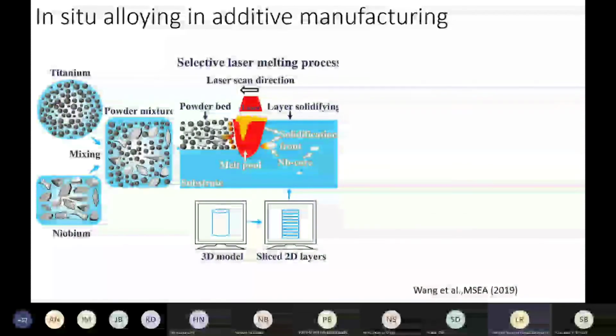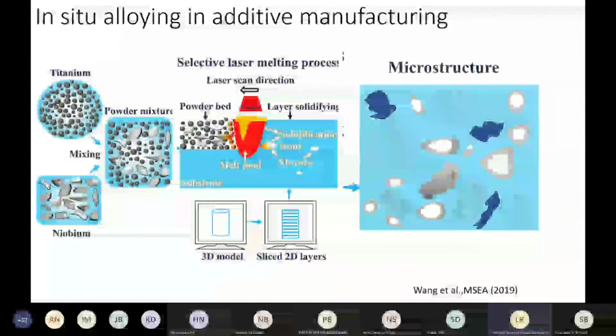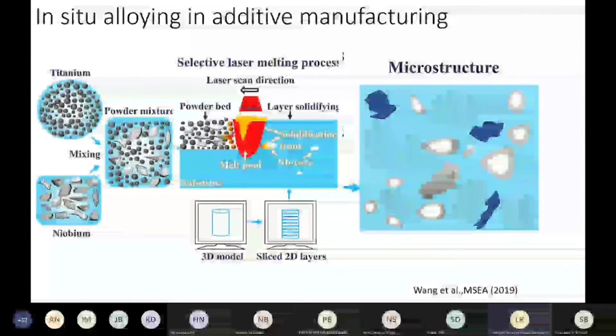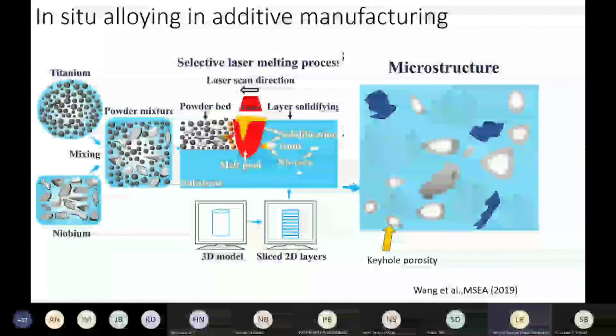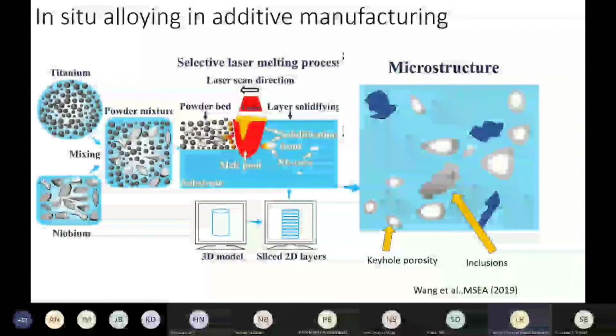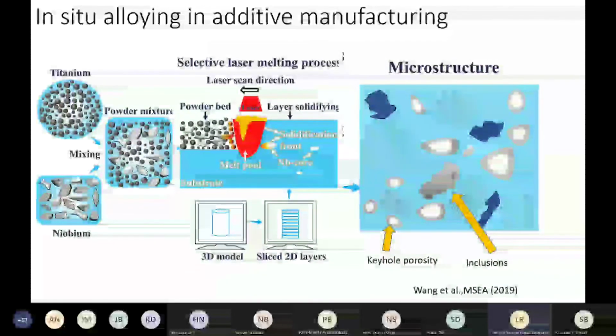This was done reasonably successfully. But unfortunately, what they saw in the microstructure was the following. They see keyhole porosities, these white spaces, as well as niobium inclusions. Okay. So these are the two defects which you don't want. You want to avoid these defects because niobium inclusions will create local clustering of grains. Okay, it leads to something known as equiaxed grains, whereas you want columnar grains. And keyhole porosity obviously has bad effects on fatigue as well as ductility. So you want to avoid these two.